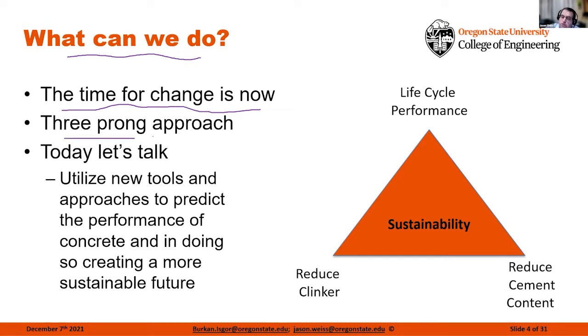We're suggesting that there's really the need for a three-pronged approach. The first is to reduce the amount of cement clinker that's used in concrete. And a great example of this is the use of Portland limestone cement. We've been really advocating for this over several, now it's going on to decades. And we've seen some major changes with new states adopting this and really moving this forward. We also think that an enormous number of our mixtures are over cemented. So we want to reduce our cementitious content in these systems. And this can be done through optimizing aggregate gradations and using performance specifications.